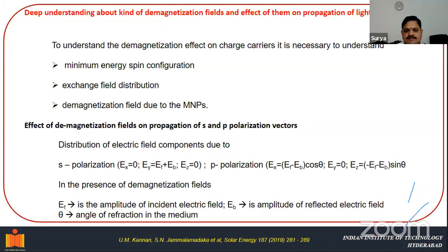Okay. So the distribution of electric field components in general, for instance, if we say S polarization, it consists of electric field component in the X direction will be 0. The EY component will be EF plus EB, and EZ component will be 0. For a P polarization, EX is equal to EF minus EB into cos theta. EY component will be 0, and EZ is equal to minus EF minus EB into sin theta. If we say S polarization, the electric field components must be like this, and for a P polarization, the electric field components will be like this. In the presence of demagnetization fields, EF is the amplitude of incident electric field, EB is the amplitude of the reflected electric field, theta is the angle of refraction in the medium.